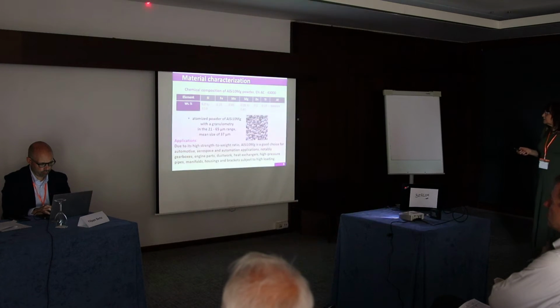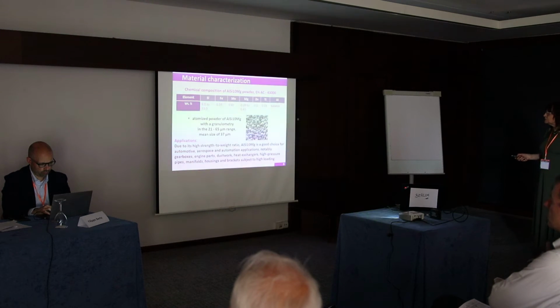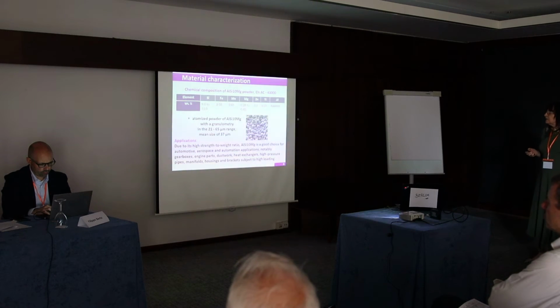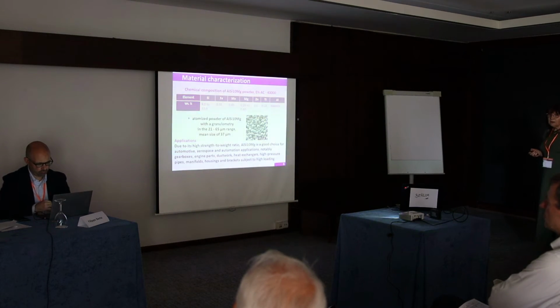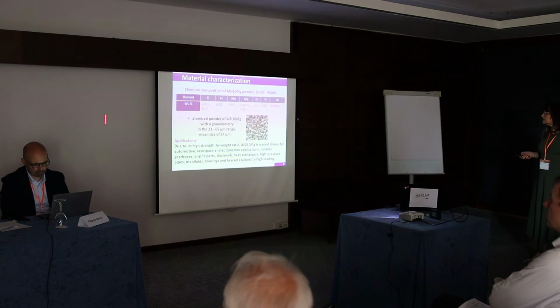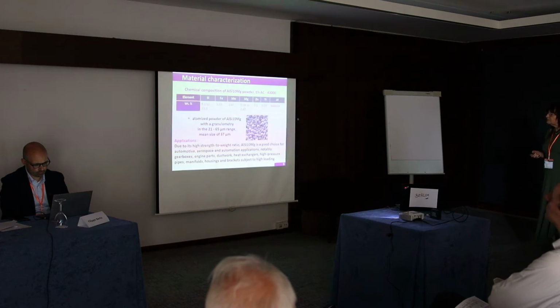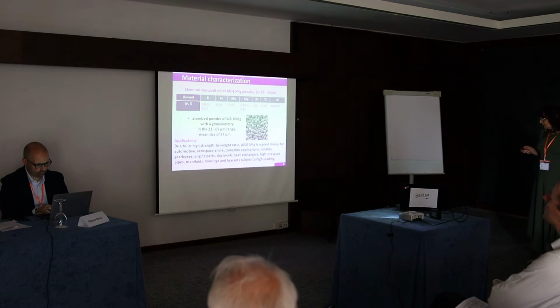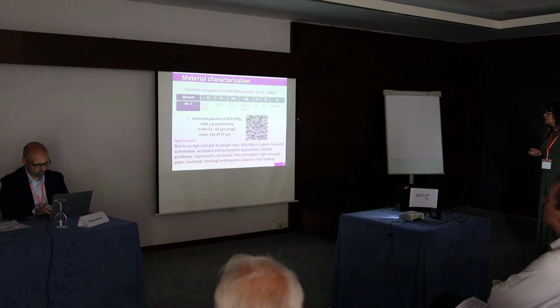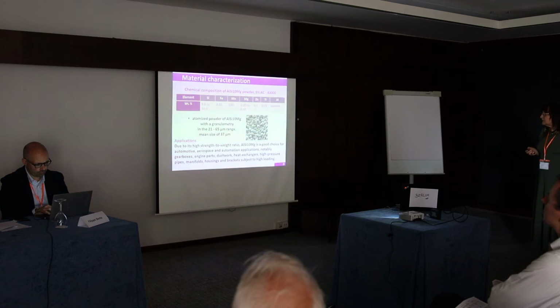The chemical composition of the aluminum alloy according to the standard is shown here. Atomized powder of the aluminum alloy has a granulometry in the 21 to 65 microns range. Mean size is 37 microns. Due to the high strength-to-weight ratio, aluminum alloys are a good choice for automotive, aerospace, and automation applications, notably gearboxes, engine parts, ductwork, heat exchangers, etc.